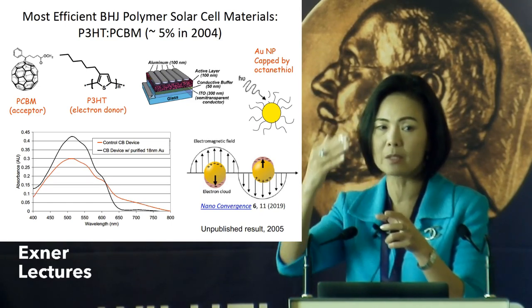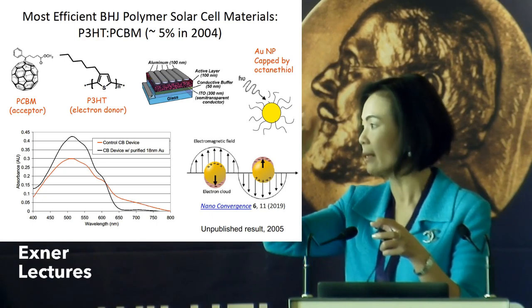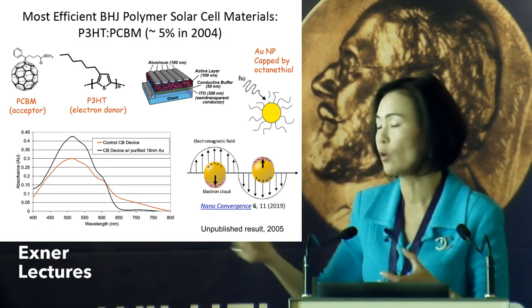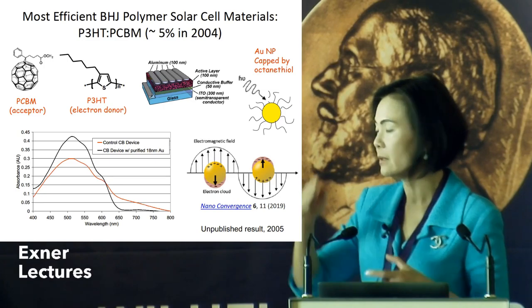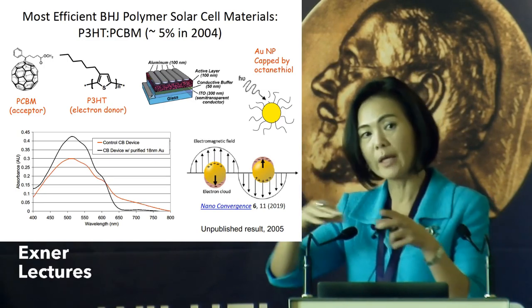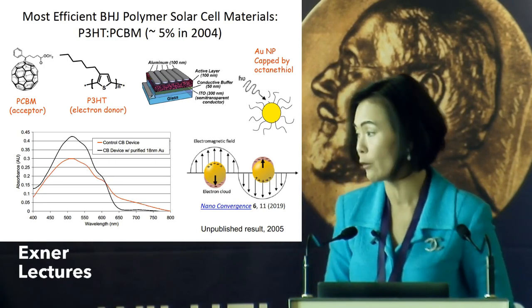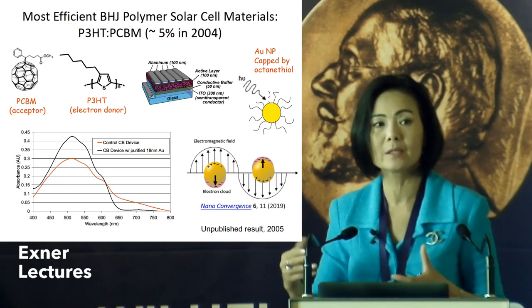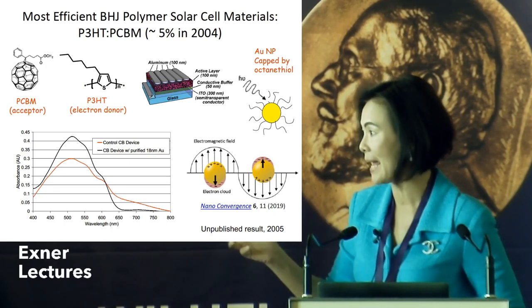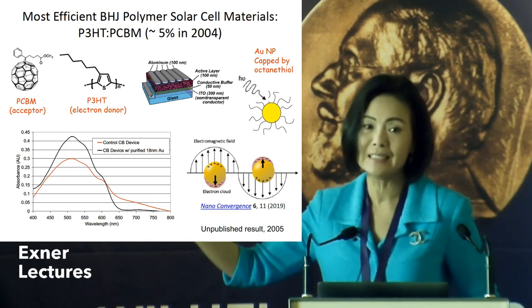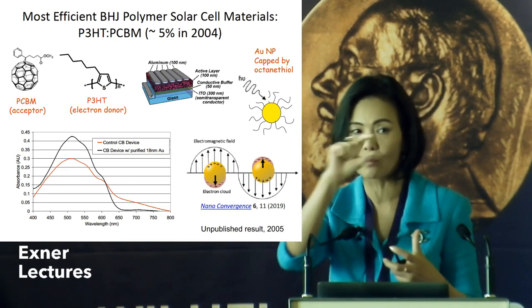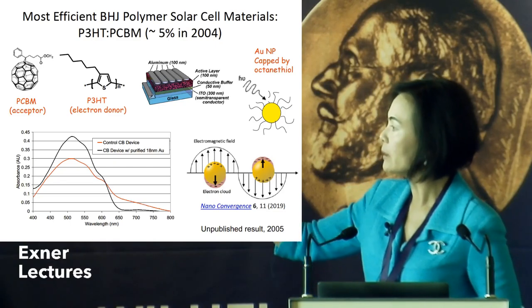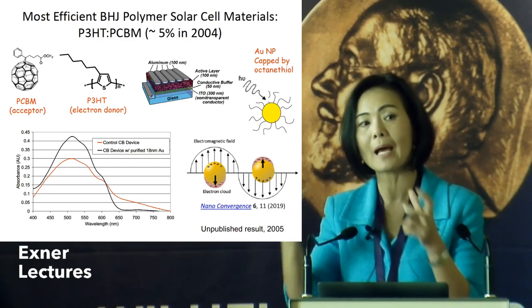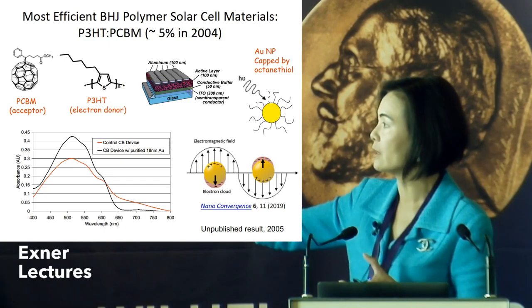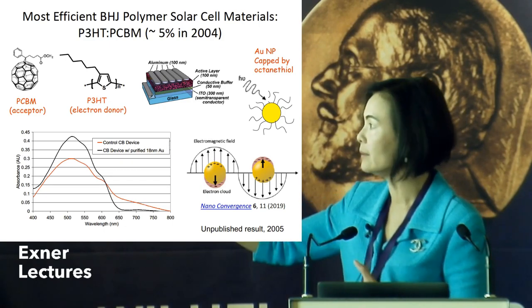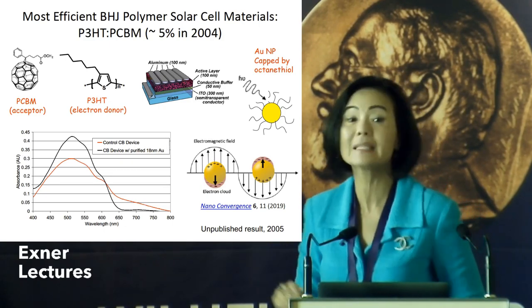you have this plasmonic effect that gives rise to the absorption of the gold nanoparticle. And this electron cloud, the oscillation of the electron cloud within the gold nanoparticle, gives rise to this intense absorption band. So the idea here was that we blend it in so that we can enhance the absorption of a very thin layer. But to make the gold nanoparticle soluble in organic solvent, the synthetic chemists have to use a ligand, and the ligand is octanethiol.